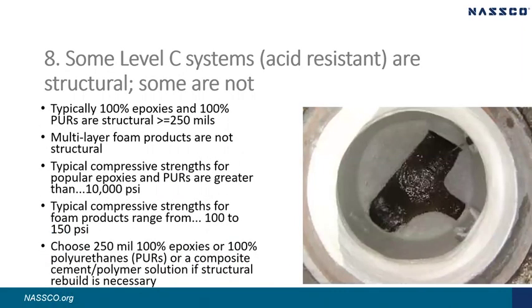Point 8. On rare occasions, there is a need to structurally rebuild an acid-corroded manhole as well as protect it against future corrosion. In those instances, a level C product that has superior compressive strength is advised. In general, 100% polyurethanes and epoxy sprayed to 250 mils or more provide structural enhancement to the structure. Typically, layered foam products do not. If structural rebuild is desired, epoxies and 100% polyurethanes should be specified at a minimum of 250 mils, or a composite system, including the enhancement provided by engineered cement, should be employed.